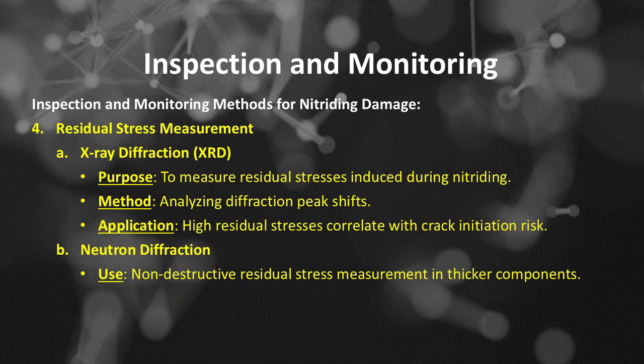Number 4 of the inspection and monitoring methods for nitriding damage is residual stress measurement. A: X-ray diffraction, or XRD. The purpose of XRD is to measure residual stresses induced during nitriding. The method analyzes diffraction peak shifts. High residual stresses correlate with crack initiation risk. B: neutron diffraction, used for non-destructive residual stress measurement in thicker components.